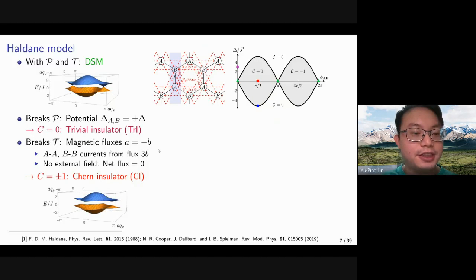Meanwhile, if we break the time reversal symmetry, we could try to realize it by introducing some magnetic fluxes on the honeycomb lattice. For example, we could introduce a magnetic flux A in this triangle and the other triangles, and we could introduce another magnetic flux B in this triangle and other analogous triangles. So what is the result of this kind of magnetic fluxes? First, let us look at the second neighbor hopping, which forms a loop around the 3 A sublattice sites. We can see that this triangle encloses 3 B fluxes. And with this kind of finite magnetic flux, it turns out that the second neighbor hopping will realize a current loop. So we will have spontaneous currents between the A sublattice sites and similarly between B sublattice sites.